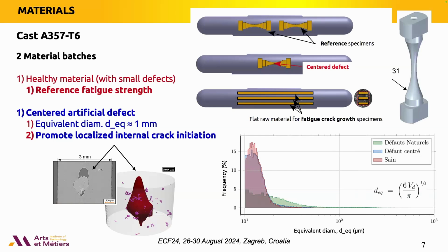And you can see it here reconstructed after tomography in 3D. So the defect is in red, and around there are pink, very small natural defects. So the idea of this central defect is to promote the crack initiation in order to be sure that where we will observe the phenomena exists and not elsewhere. We have also produced some flat specimens for classic crack growth measurement with classic fatigue testing.